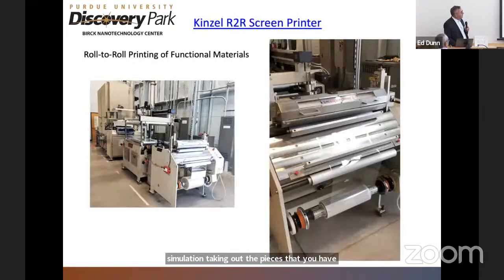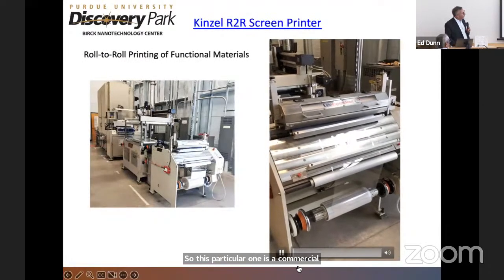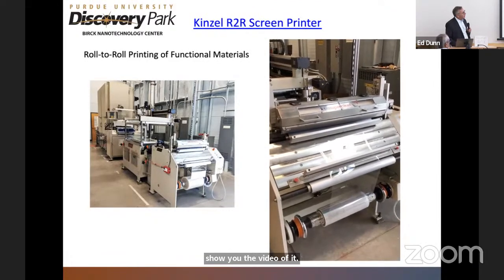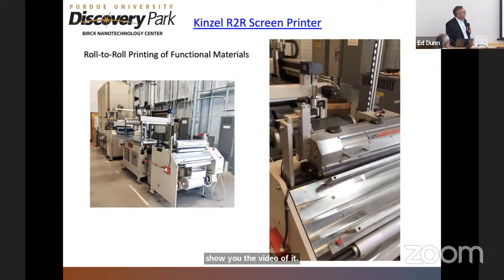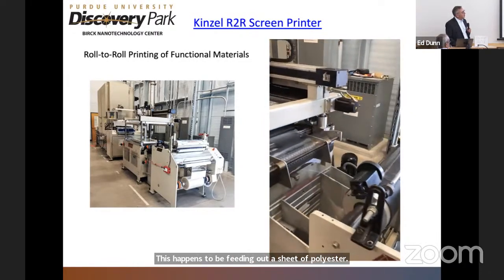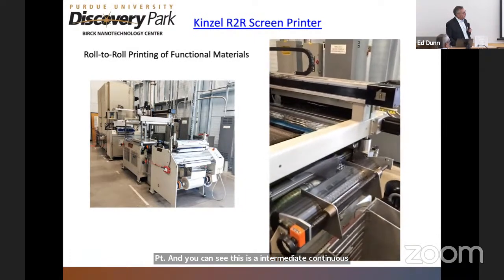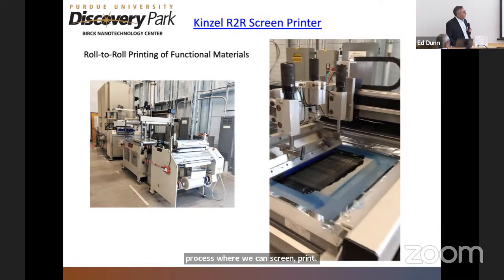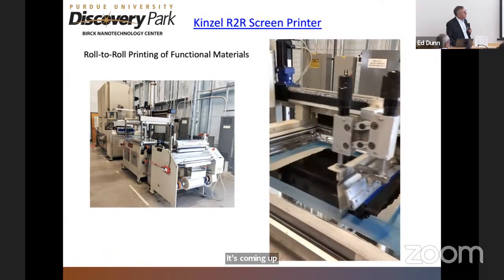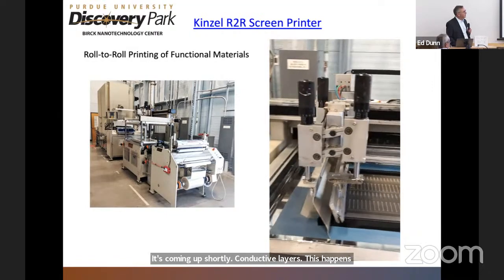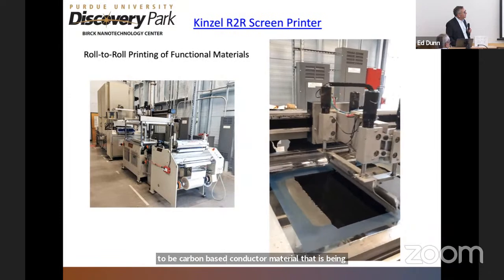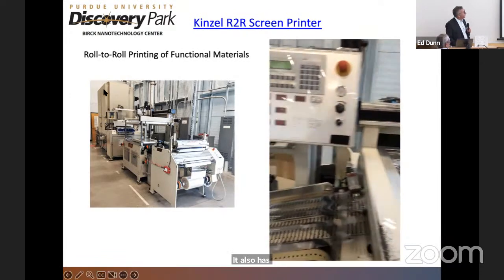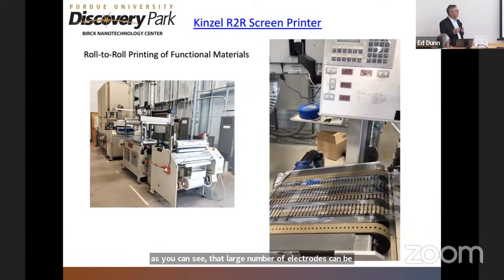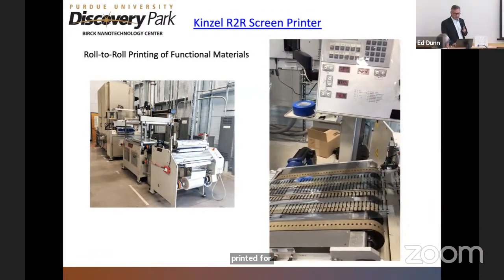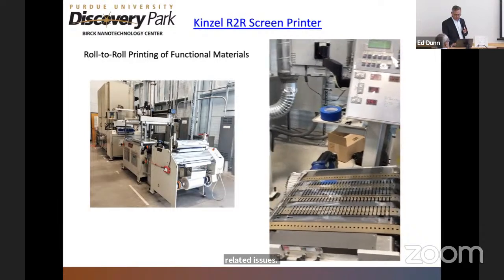So this particular one is a commercial machine, and I'll show you the video of it. This happens to be feeding out a sheet of polyester, PET, and you can see this is an intermittent continuous process where we can screen print. It's coming up shortly. Conductive layers. This happens to be carbon-based conductive material that is being printed. It also has towers that you see here that do the curing. As you can see, a large number of electrodes can be printed for further statistical analysis and other related issues. So this is essentially a scale-up process.